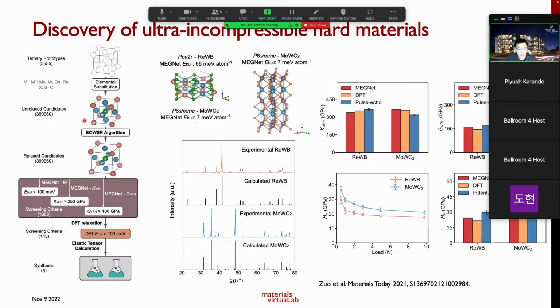What we then do is use our Bayesian optimization algorithm to relax the crystal structure, and then we screen based on machine learning property predictions. And then we narrow down the candidates to about 1,000. And then finally, we just do DFT calculations on 1,000 structures to get about 143 potentially stable structures. And finally, our experimental collaborators, the group of Professor Xian Luo, went ahead to try to synthesize 8 of them. And we actually managed to get all 8 new crystal structures.